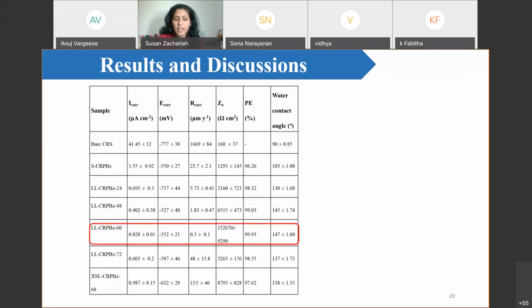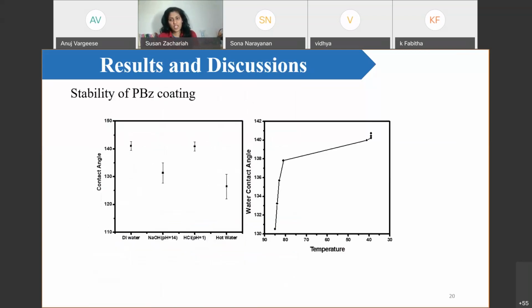So we compared Xanthosoma sagittifolium leaf also at the 60-hour pre-treatment, and the best sample, which is Lotus leaf based 60-hour pre-treated cross-linked PBz, gave a water contact angle of 147, an I-corr value of 0.028, and a protection efficiency of 99.93%. We also checked the stability of the PBz coating later on.